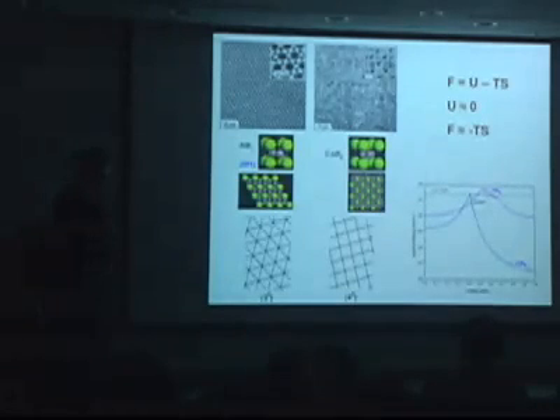the crystallization process. With nanoparticles, we can very precisely tune the sizes of both components. For each of these lattices, we have a space filling factor, a space filling curve, that pretty directly plugs into translational entropy during the self-assembly process. Now we can tune the ratio of particle sizes in such a way that these two curves cross. They cross at a gamma ratio of 0.43.